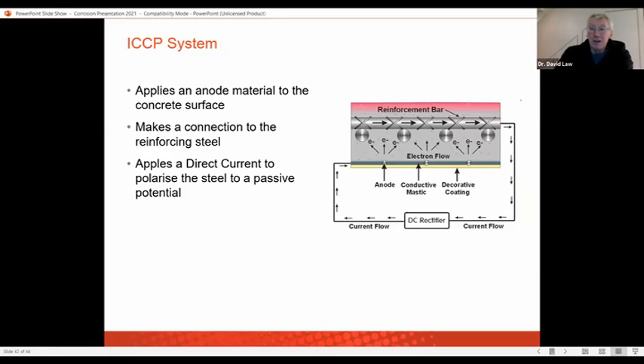But the ICCP applies this DC current for a long period of time. These systems, 20, 30, even 40 years now, these are applied for. When you're talking about hybrid, you're probably talking about 6 to 8 weeks, and you're really using large batteries to apply that current.